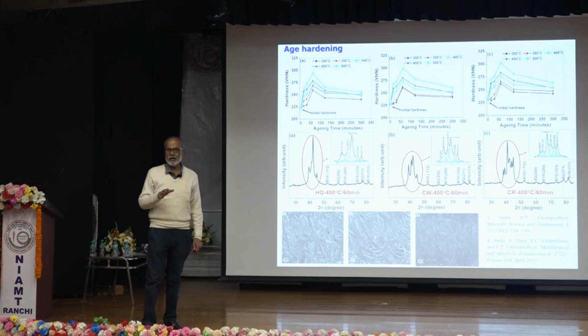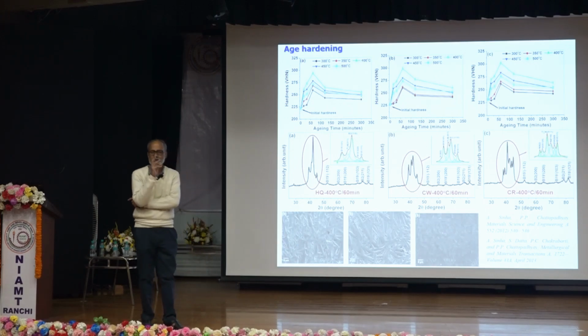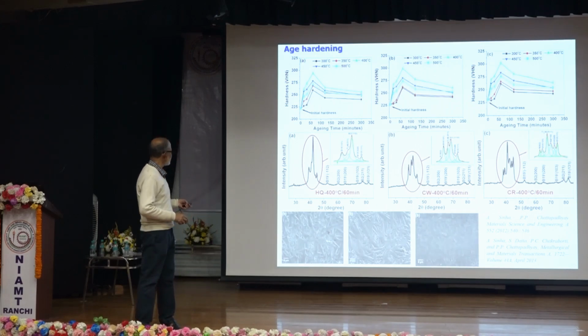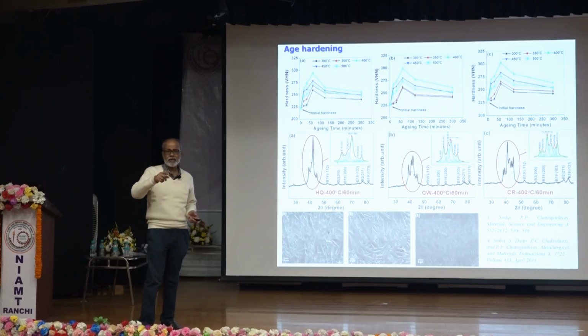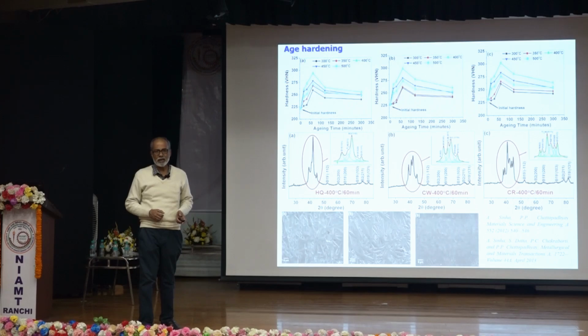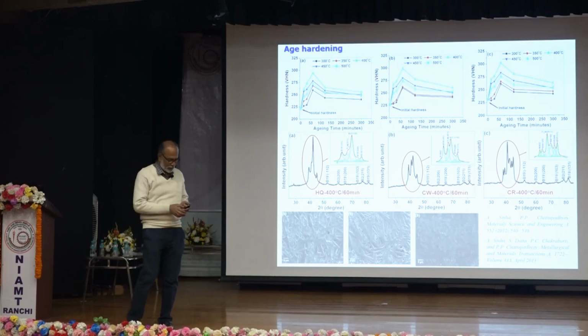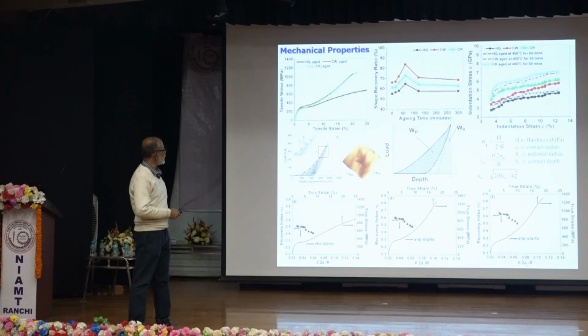Deformation will cause straining of the matrix, and when there is precipitation, there are three major effects. Number one, as it is titanium rich, the region around the precipitate will get depleted in titanium, right? And that will change the Ms temperature. Second thing, these precipitates will create a coherency stress because it has to be stabilized within the matrix. I believe metallurgy students are familiar with coherency strain. So the coherency strain hinders martensitic transformation. But the precipitate provides the surface for nucleation of martensite and helps in martensitic transformation. So the role of the precipitate itself is conflicting. So frankly speaking, we were very confused in correlating the structure and property.